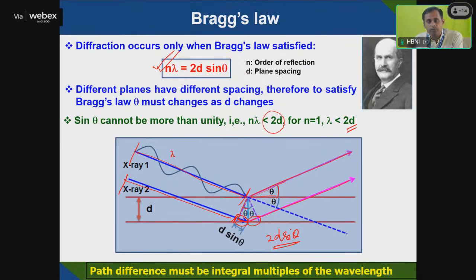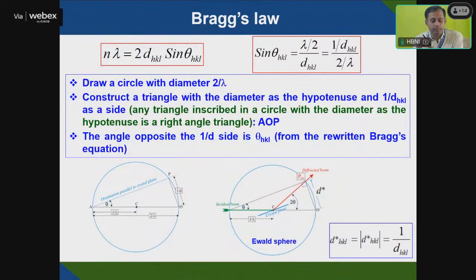As you know, for most inorganic systems the d spacing lies at the angstrom level, and the copper K alpha target commonly used for X-ray has a wavelength of about 1.5405 angstrom. If you take this copper K alpha lambda, it is within the 2d limit of the lattice spacing between two planes, so you'll be able to see these things. So the path difference must be an integral multiple of the wavelength lambda. This is the equation n lambda equals 2d sine theta.